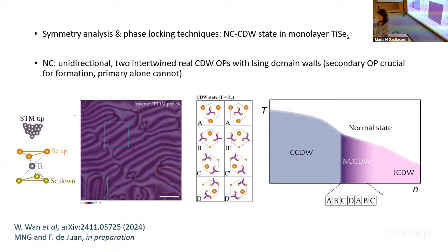When you do the Fourier transform, you get all the harmonics contribution from the lattice. So you'll have the ones from just the Bragg peaks, let's say. Then you'll have the new order, and then you can select those and Fourier transform back. Those have to do with that wave vector, which in this case is half of the Bragg peaks. And then you go back to real space of where that charge density wave order parameter lives. You focus on the M point because this is where the superconductor comes from? No, I focus on that one because that's where.